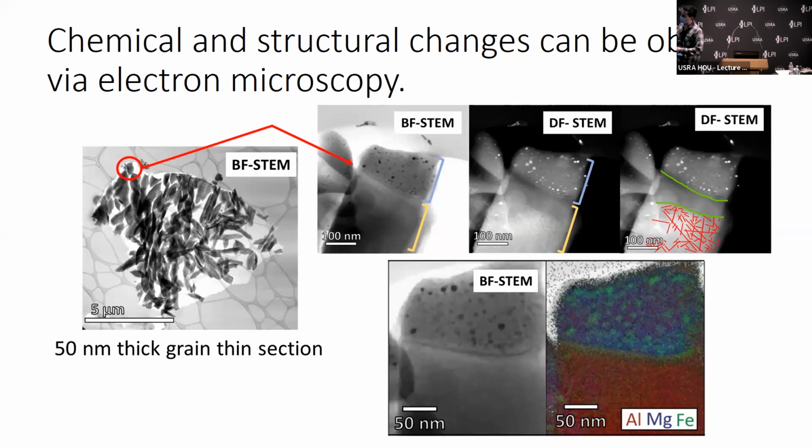And then in the grain interior, we have a solar wind damaged rim that's marked in green here. That's formed through low energy solar wind ions, primarily hydrogen and helium, that can penetrate nanometers in depth beneath the surface. And just below that, we have solar energetic particle tracks that are traced in red. Those form through higher energy particles from the sun, primarily iron group nuclei, and they can penetrate millimeters in depth beneath the surface.